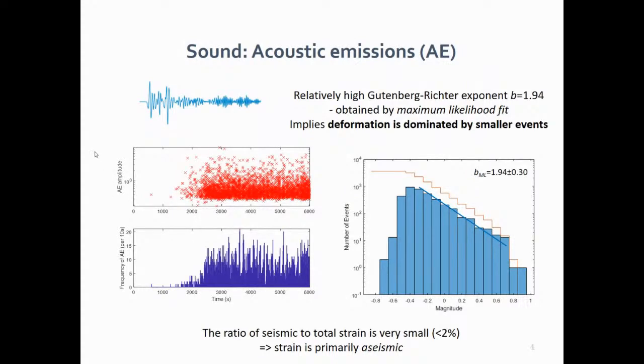The acoustic emissions themselves, this is just the usual. We measure the maximum amplitude as a function of time, and these are all the data points, and from that you can work out the frequency of events. It's kind of constant, plus or minus quite a bit of scatter in the feedback control. The frequency magnitude distribution gives us a relatively steep slope, just under 2. It's not completely atypical of induced seismicity, actually. Normally for earthquake seismicity, this is around about 1.